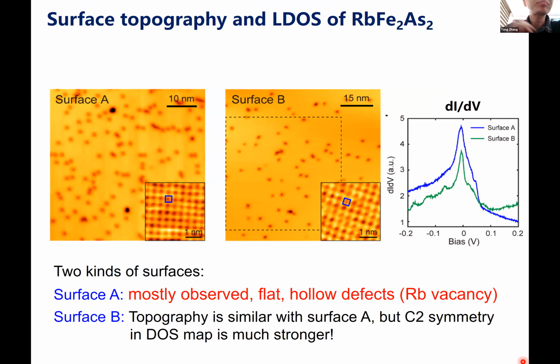Now here shows the topography of the cleaved rubidium 1-2-2. Here I show two types of surface, A and B. Surface A is the most commonly observed, about a 90% chance. But actually, these two surfaces have the same lattice. The only difference is their symmetry breaking in the dI/dV mapping. I'll show it later. But in the dI/dV spectra, they both show a DOS peak at the Fermi level, which is similar to the potassium 1-2-2 system.